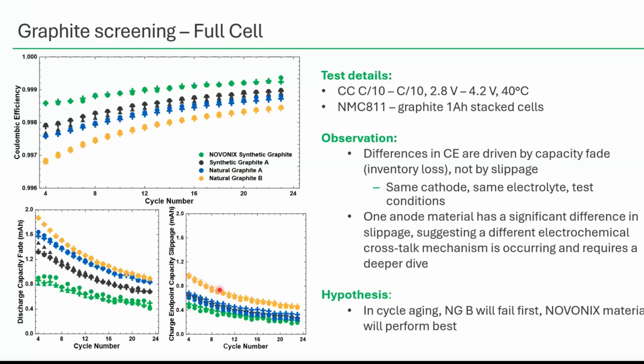We do see a very consistent outlier here. Those pair cells are quite consistent, and this slippage is a little higher. This points to something else happening in these cells, where maybe there's a mechanism happening at the anode which is generating some type of crosstalk mechanism, something that ends up being unstable at the cathode, but actually originates due to some SEI byproduct.